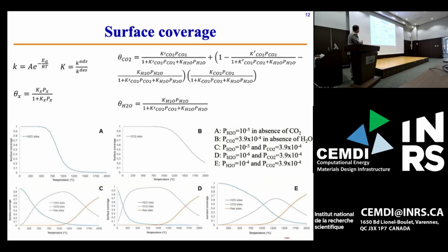The results show that at low temperature, the surfaces are mainly hydroxide. As you increase the temperature, the hydroxide will be slowly evacuated and replaced by carbonate. At operating temperature, only a small amount of the surface would be hydroxide and oxide, and most of the surface would be carbonate, so the active sites will be rather limited. If we have dry conditions, the carbonate will be formed at much lower temperatures, reach almost 100%, and block the active sites on the surface.